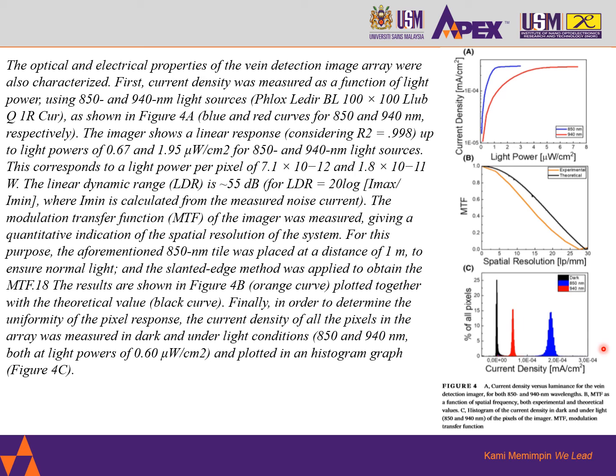The linear dynamic range is 55 dB, for LDR equal to 20 log Imax by Inoise, where Inoise is calculated from the measured noise current. The modulation transfer function, MTF, of the imager was measured, giving a quantitative indication of the spatial resolution of the system. For this purpose, the aforementioned 850 nanometer tile was placed at a distance of 1 meter to ensure normal light, and the slanted edge method was applied to obtain the MTF. The results are shown in figure 4b. Here we can see the orange curve plotted together with the theoretical value, the black curve.